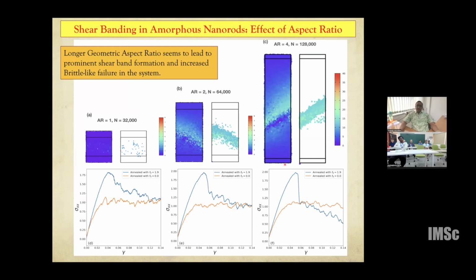These are the pillars which are annealed using active particles, or you can also anneal them by oscillatory shear. I did not talk about it in detail. If you take this system with aspect ratio 1, so basically a cubic pillar, and you pull it, the shear bands are not very clean. But if you take a pillar with aspect ratio 2, height versus the base, then you get a shear band which is much cleaner than the cubic one. If you take an aspect ratio close to 4, then you get a very clean shear band. And if you look at the corresponding stress-strain curve, you see a very sharp drop.